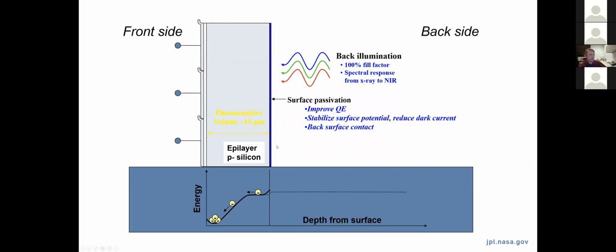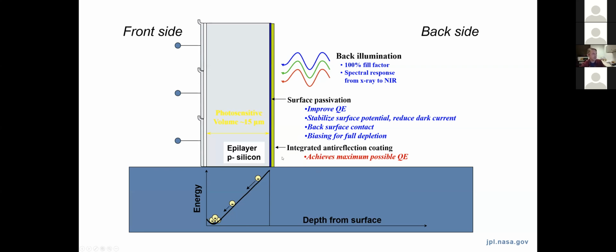But then this delta doping passivation creates a favorably energetic profile such that charge carriers can now be detected. There's the additional benefit that by introducing such a high doping concentration to the backside of this device, it's now electrically conductive as well. And that means you can do things like apply a bias to improve the depletion of your photosensitive volume. So this can be important both for thin sensors in this range of 15 microns, but also thicker devices as well, where it might be hard to otherwise fully deplete this volume, and give these charge carriers an additional energetic push and really make sure that they're detected. And then later I'll talk about